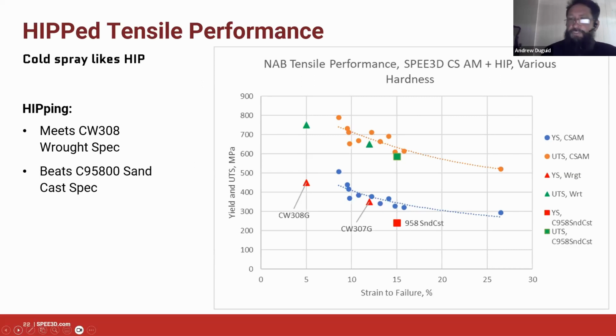So this was a fantastic result for us, and frankly above expectations. You see the square red dot there is the yield stress value for the C958 sand casting specification, and the green square above that is the UTS requirement. We're meeting those requirements pretty comfortably. We've got a margin whichever way you want to look at it. We've either got a margin on strength or a really pretty significant margin on elongation over the sand cast spec. That's a fantastic outcome for us, and we're really happy about that.